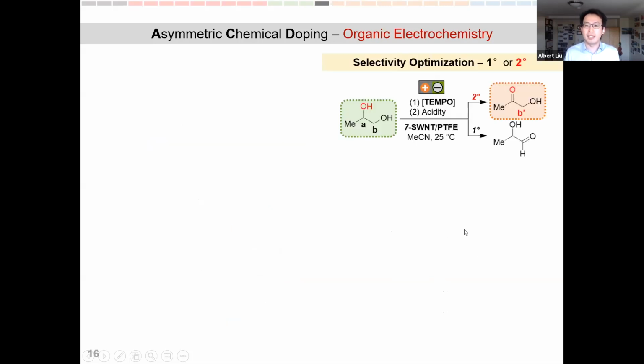In order to showcase the utility of having a particulate generator, we devised a selectivity optimization problem in which we try to oxidize 1,2-propanediol. Basically, we can oxidize this alcohol in two locations, one at the primary location, generating this product, and one at the secondary location, making this kind of product. In this problem, we ask whether we can screen for a condition that will selectively produce the secondary alcohol oxidation, which is the harder carbon to oxidize. And we tune our reactivity by changing catalyst loading and the Lewis acidity of the organic solvent.